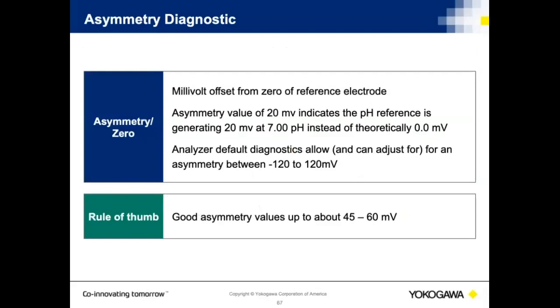Asymmetry. What it's looking at, remember the equation that said E equals E sub 0 times the output of the measuring electrode, or plus the output of the measuring electrode. Well, that E sub 0 is going to change with time. And that E sub 0, I cannot make an identical reference electrode. So what I have to do is compensate for, number 1, the difference in the measuring and reference electrode, and as it ages. A good measuring electrode or good reference electrode is always going to have an asymmetry value of plus or minus 45 millivolts.